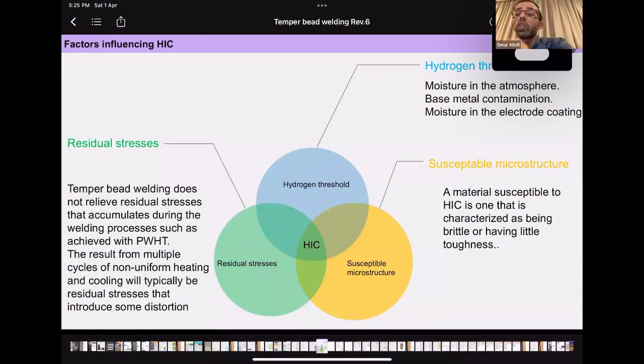Okay, hydrogen-induced cracking can be affected by three factors: the hydrogen threshold, residual stresses, and susceptible microstructure. So the diffusible hydrogen in the electrode, any moisture in the atmosphere, base metal contamination, or moisture in the electrode coating can increase the hydrogen content and can increase the likelihood or probability of having hydrogen-induced cracking.